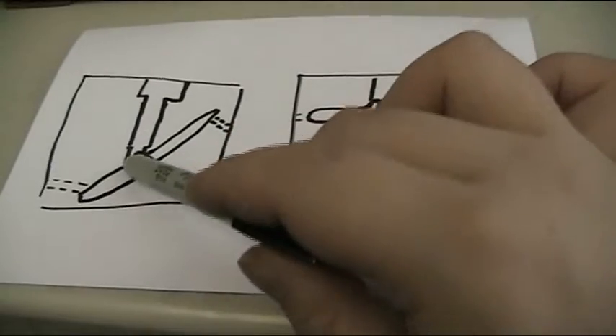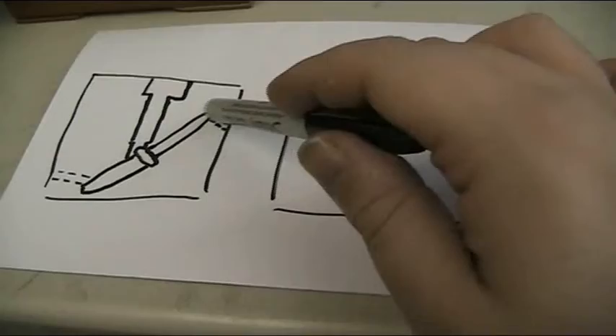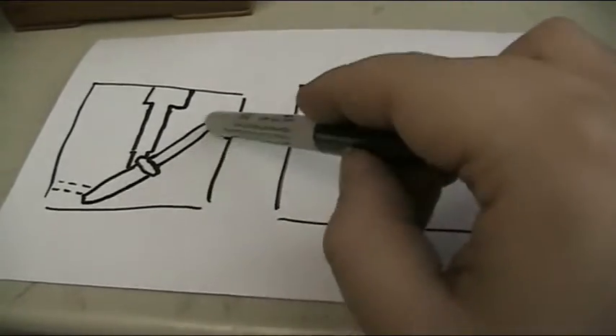I've got the knife on an angle so it could go in the thick area. And later on, as it kept cutting halfway, I carved out a vent so there was a little sprue hanging out that I could trim later. After I cut out a little vent and held the plunger down for 30 seconds, we started getting a full piece.